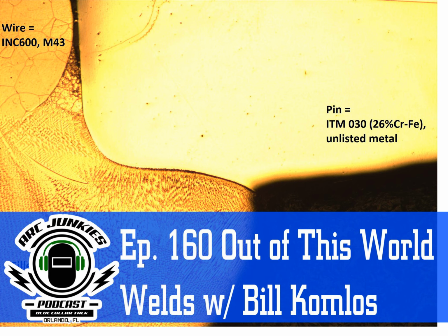And we were welding out, just about finishing it up, and the guy's putting in the sub-arc pass on the inside, and he hits some of this grody metal, and all of a sudden you see one of these sparklers go off. You know how you hit dirt and it sparkles on you? Well, it was just like that. And that thing, the 7-foot diameter can, 1.5 to 2 inch thick with this cladding, it cracked. The head cracked all the way around at the speed of sound, just boom.